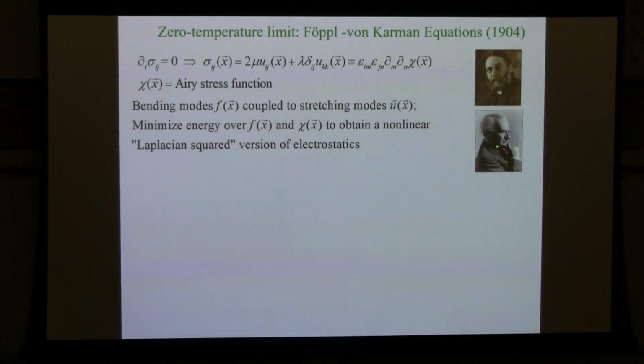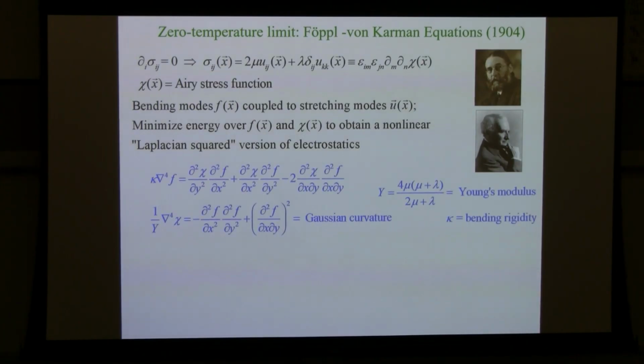Here's Foeppl, here's von Karman. And what they did was they said, well, if you look at the nonlinear stress matrix, which is related to the nonlinear strain matrix in this way, at zero temperature, it satisfies this zero force balance condition everywhere. And so just like the no magnetic monopoles condition of electricity and magnetism, that means you can write this thing. Actually, in this case, it's an anti-symmetric contraction, with a summation convention, over these two derivatives of an Airy stress function. And so if you put that in, there's an Airy stress function that describes the in-plane stresses. There's still this F field. And if you just do a little functional minimization over that nonlinear energy, you'll get these Foeppl-von Karman equations. They were discovered in 1904.